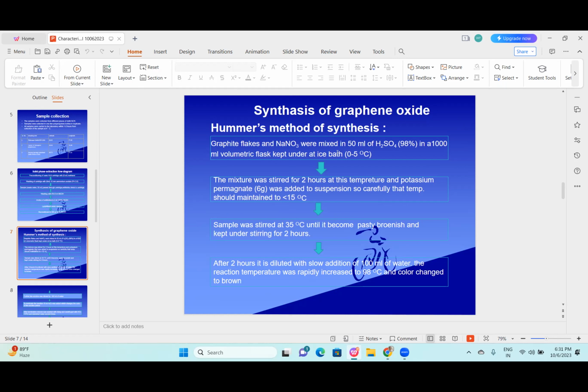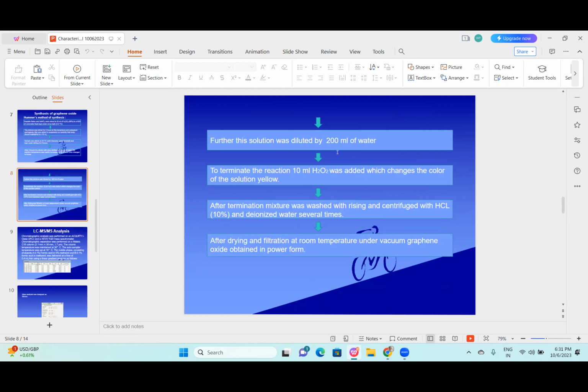After 2 hours, it is diluted with slow addition of 100 ml of water. The reaction temperature was rapidly increased to 98 degrees centigrade. Color changed to brown. Further, this solution was diluted with 200 ml of water. To terminate the reaction, 10 ml H2O2 was added, which changed the color of the solution to yellow. After termination, the mixture was washed by rinsing and centrifuging with 10% HCl and deionized water several times. After drying and filtration at room temperature under vacuum, graphene oxide was obtained in powder form.